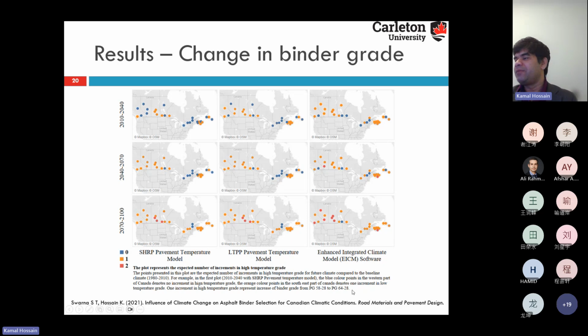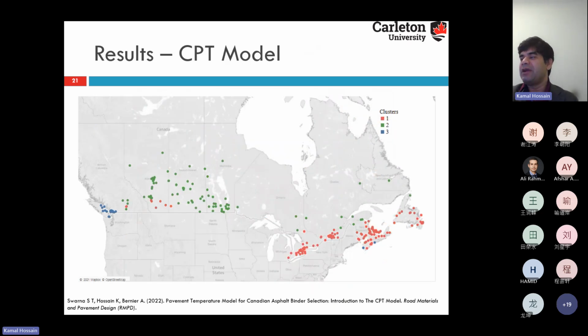So you can see it's already explained in the graph as well. One increment in high temperature grade represents an increase of binder grade from PG 58-28 to PG 64-28. So -28 is the low temperature. In this particular case, we did not see the low temperature needing to be changed. But in some regions, we saw that the low temperature grade also needed to be changed. Again, the details are in this paper. It's also published.